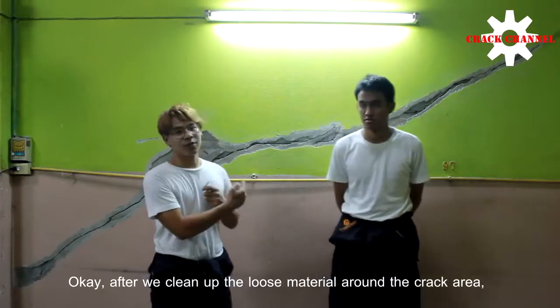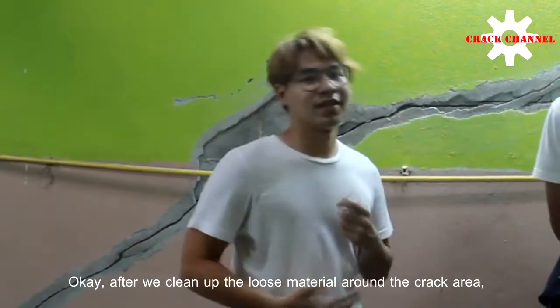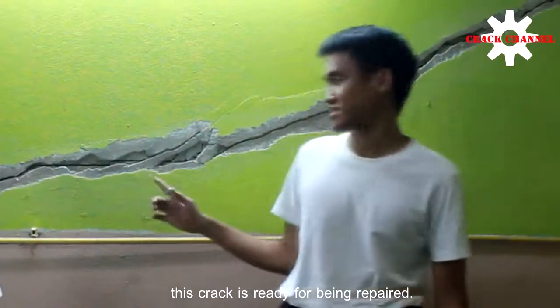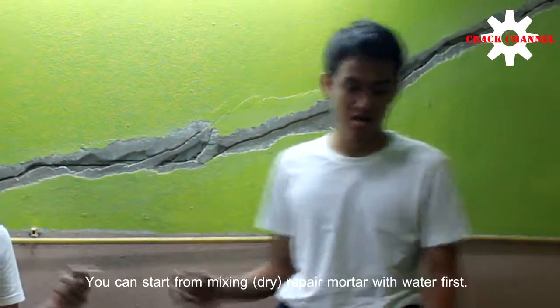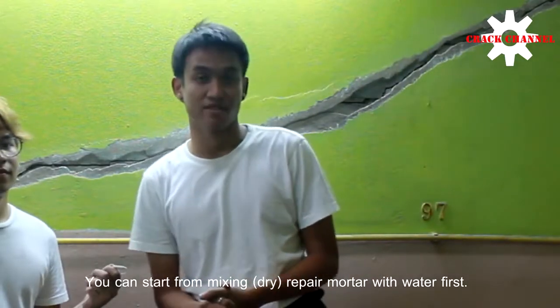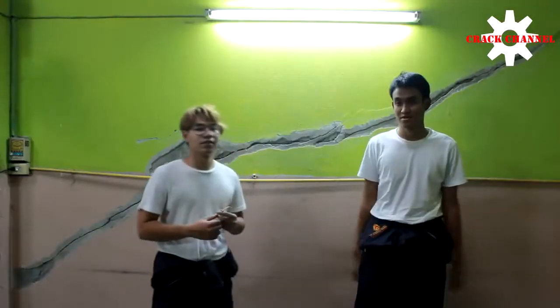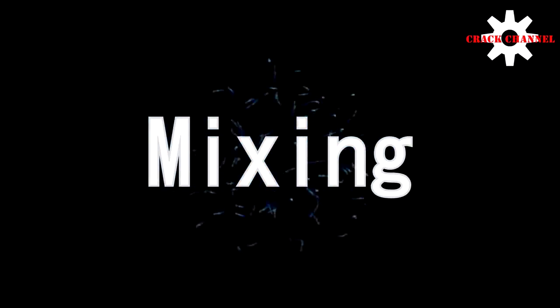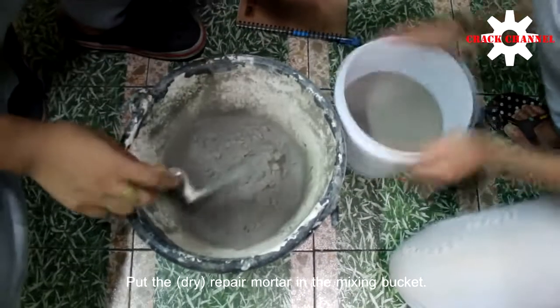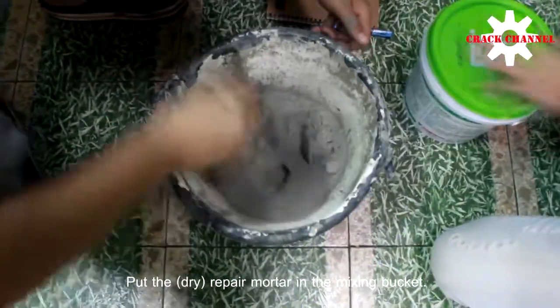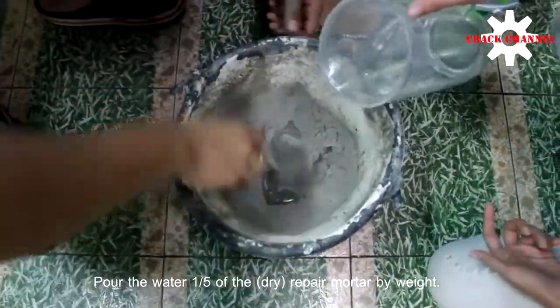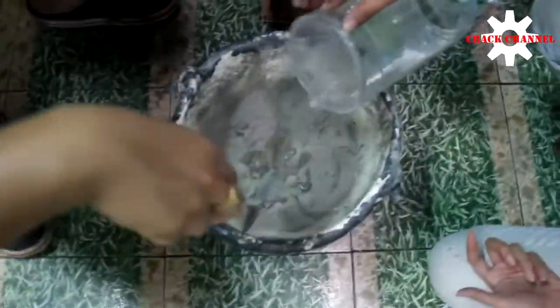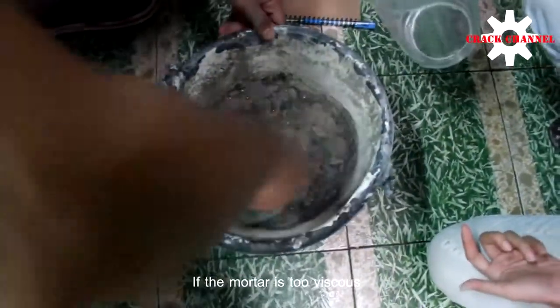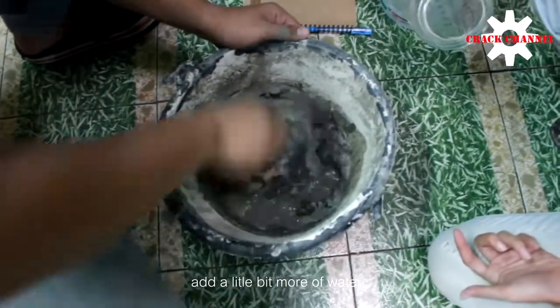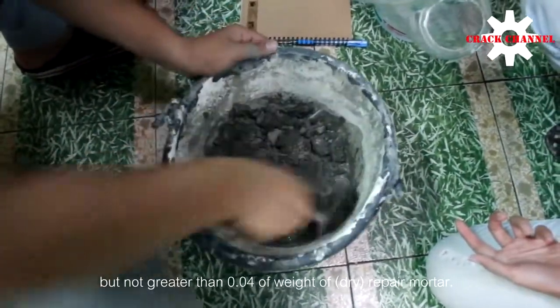Okay, after we clean up the loose material around the cracked area, this crack is ready for being repaired. You can start by mixing repair mortar with water first. Put the repair mortar in the mixing bucket. Pour the water, 1/5 of the repair mortar by weight. If the mortar is too viscous, add a little bit more water, but not greater than 0.04 of the weight of repair mortar.